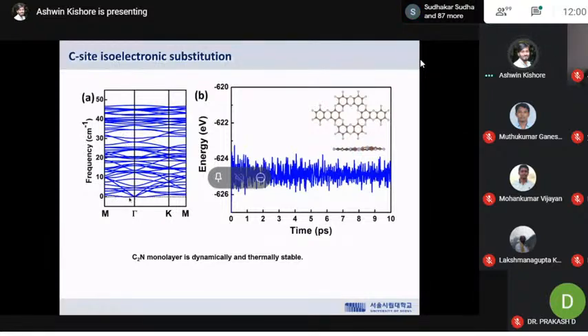They are positive, and there are no imaginary frequencies. That means the material is dynamically stable. And then to check that the material is stable at room temperature, we performed ab initio molecular dynamics at 300 Kelvin for about 10 picoseconds.